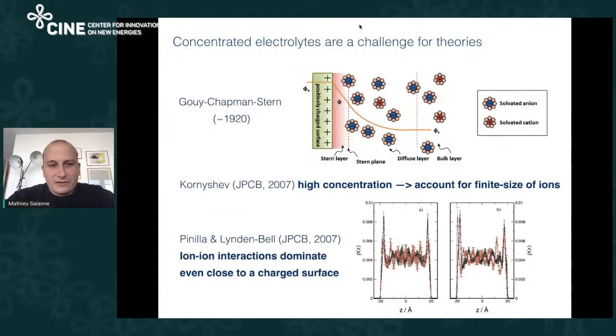However, there are several difficulties that need to be tackled when trying to understand supercapacitors at the molecular scale. The first one is that, in fact, we are dealing with concentrated electrolytes. So we have a liquid which contains a lot of ions. And this is a difficulty because, when you look at electrochemistry textbooks, you have this Gouy-Chapman-Stern picture of the interface between an electrode and a liquid. But this picture only holds when you have very dilute electrolyte. And even this picture which I show here is wrong. When you start to have such a concentration of ions, it doesn't work anymore. And you start to have very strong interaction between the ions, and you cannot use a simple theory anymore.